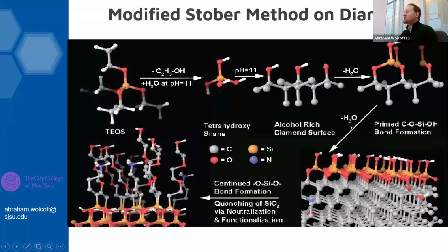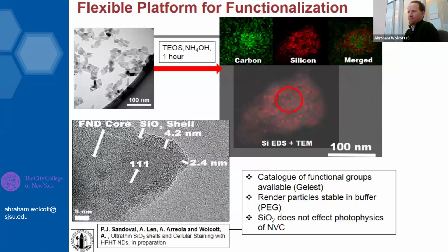It's a polymerization reaction, a condensation reaction, and water continues to leave, and you can prime the surface and continue to grow silica. Then when you finish that chemistry, you can decorate the surface with polyethylene glycol or amines or any number of different functional groups. But what happens to the diamond during that process? And is my picture in the middle of the alcohols being involved accurate? You should be suspicious of that.